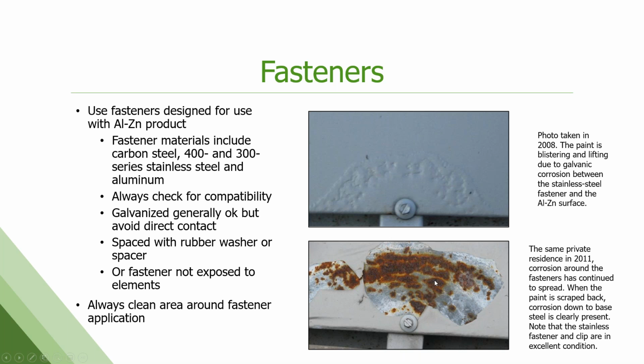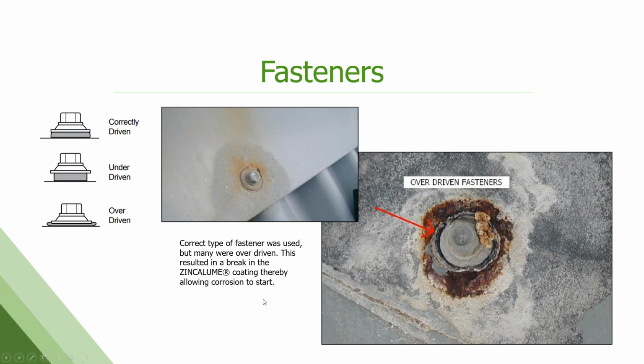So we went back in 2011. It's just continuing to get worse. This galvanic corrosion will occur until this panel is completely rusted through and gone. So now we're getting red rust, right? There's no metallic coating left. The paint's come off, and we're down to base steel. But you'll see that the stainless looks fantastic still. And that's galvanic corrosion.